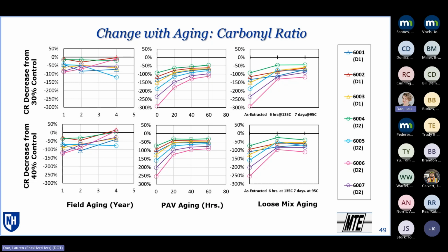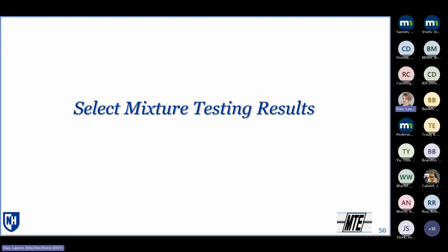With respect to the 30% control, with the 40% control, you're seeing, again, those coming a little bit closer. With the PAV aging, no obvious trends in terms of what's happening. And then same with the extracted and recovered from the loose mix aging. So that's just a quick snapshot of some of the binder results, and now some of the mixture testing results.